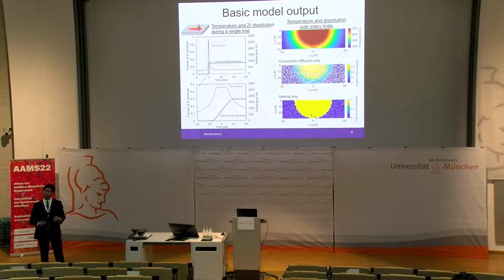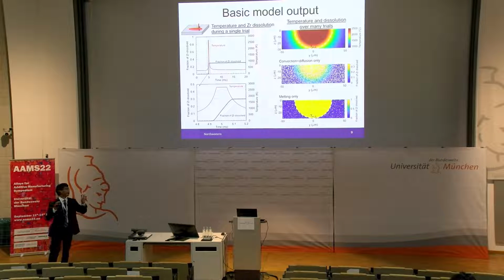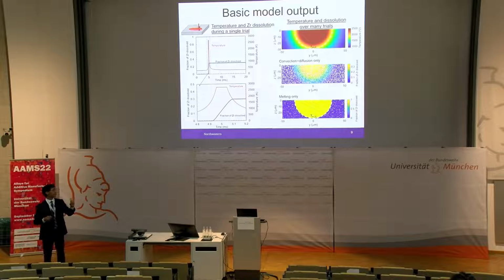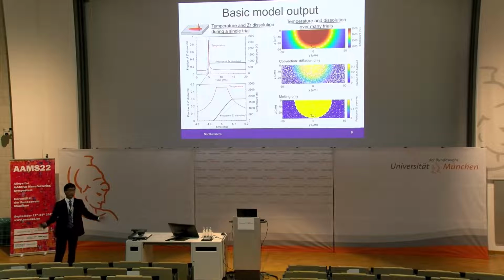We then have to recognize that the zirconium particle can really be anywhere with respect to the laser. Since this position has a strong effect on the temperature, and therefore the amount of dissolution, we perform this trial many, many times for random locations of the zirconium particle, and then for a given set of process parameters, we estimate how much zirconium is dissolved by taking an average over all these trials.